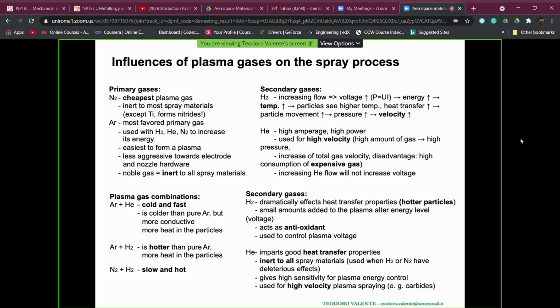The plasma gas combinations which are usually used in industry see the combination of argon and helium. This combination, in the ratios which are referred to the powder composition, can give a colder, we should say, but faster plasma. Argon and hydrogen is a mixture giving us a plasma hotter with respect to the use of pure argon, that is hotter on the particles. The combination nitrogen plus hydrogen gives a hot plasma plume due to the presence of hydrogen, but a slightly slower plasma plume itself, that is the velocity.